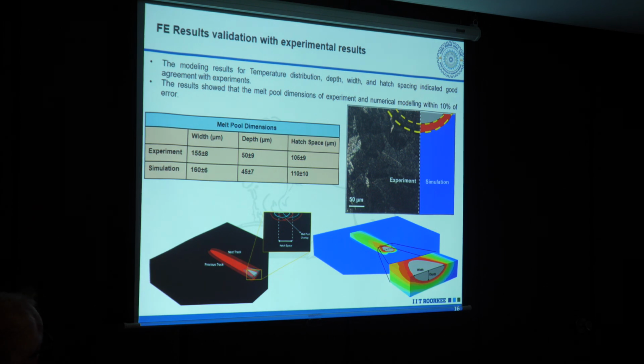We validated this by doing optical microscopic analysis of the as-printed specimen. In that case, we evaluated the melt pool depth and width. This is our experimental width that we obtained. 155 microns is the average width, with a standard deviation of 8. And in simulation, we observed 160 microns with a standard deviation of 6 for the width. This is your hatch spacing, the spacing between two melt pools. So you see the simulation result is within 10% error.